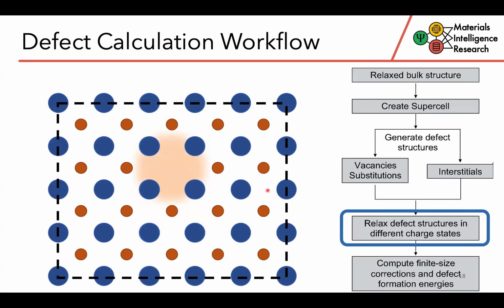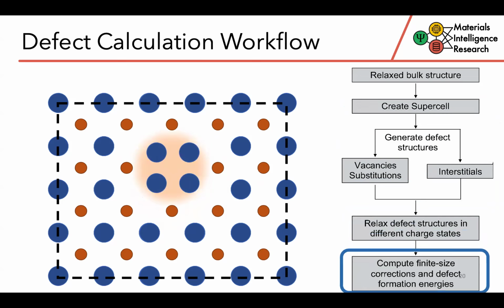Essentially, with this initial defect structure, we then relax the structure to obtain a ground state or equilibrium geometry. And then finally, we can calculate the formation energy, or essentially the single point energy, of this relaxed structure.